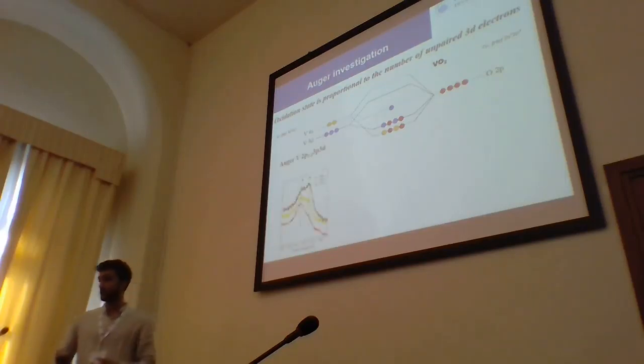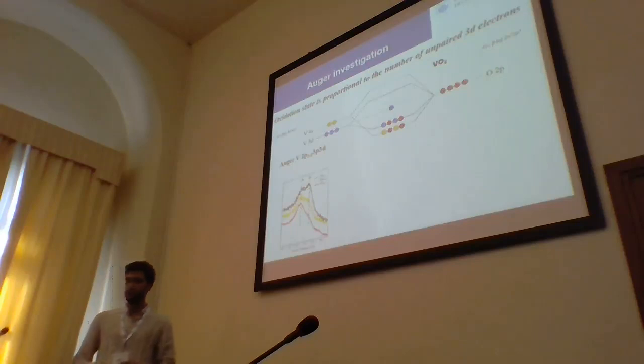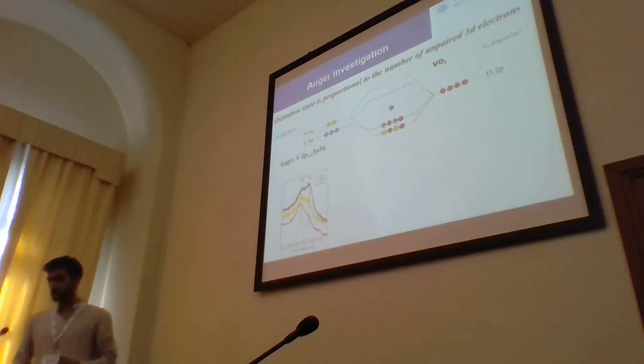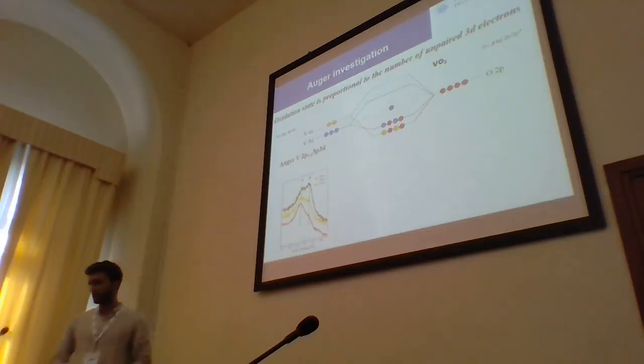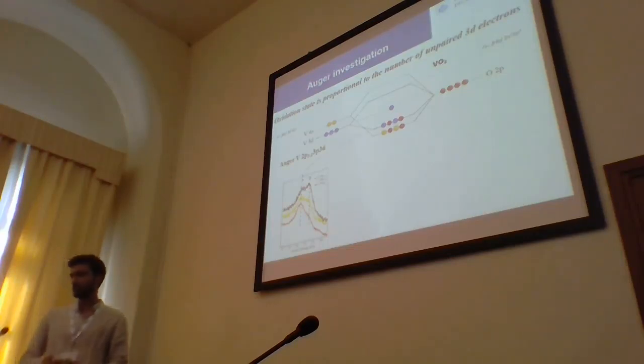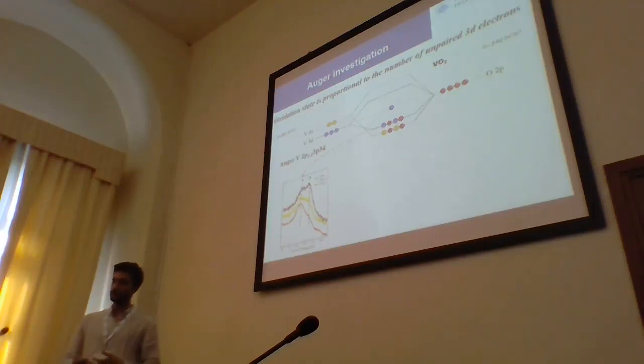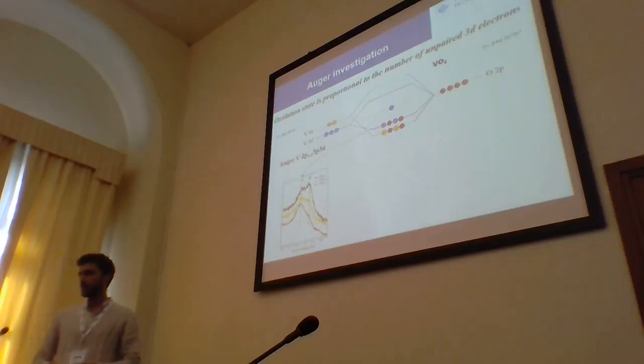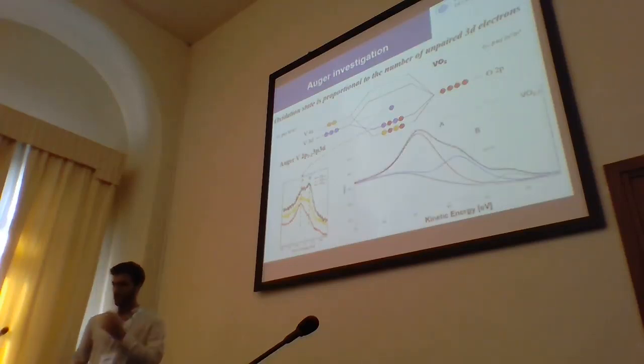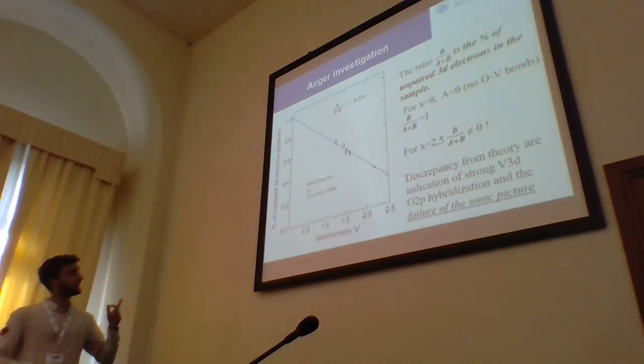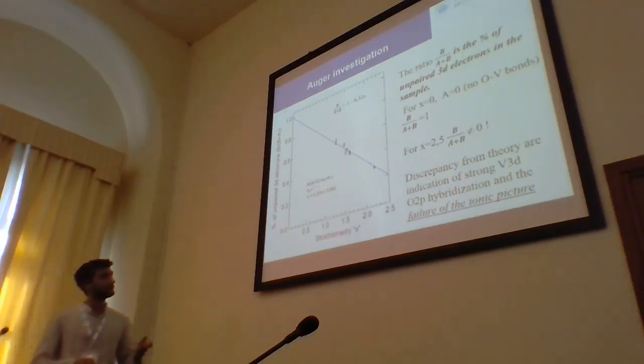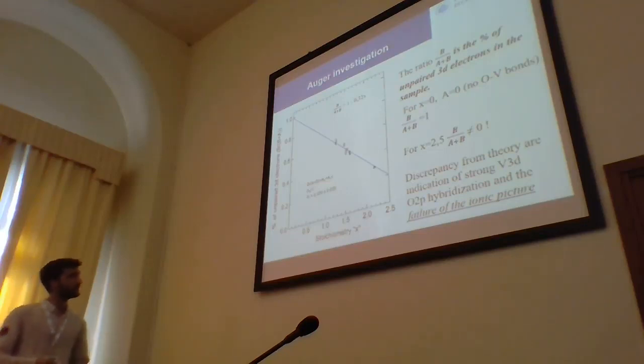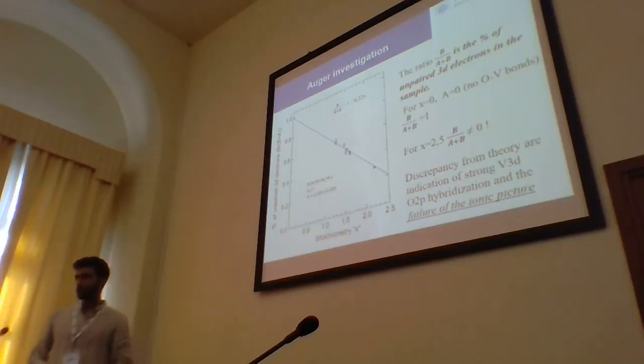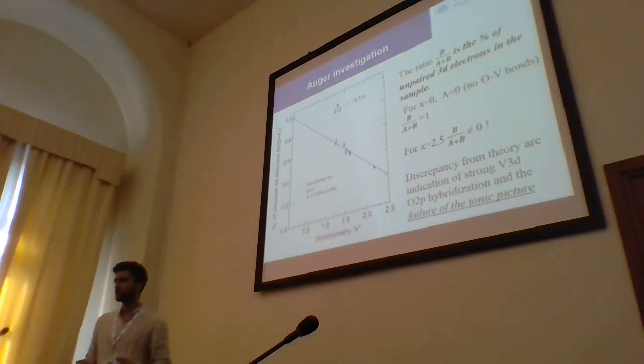So looking at the Auger 2p 3/2, 3p, 3d, we see that as a function of the oxidation state, there are two features that, using all my imagination, I called A and B, which evolve with the oxidation state. I was able to link the A feature to the 3d electrons of vanadium which are bound to oxygen, and the B feature to the unpaired 3d electrons. Again, fitting these two features, I was able to extract quantitative information, and in particular the ratio of the area of the B feature with respect to the sum of the A plus B features is the percentage of unpaired 3d electrons in the sample. As you can see, this quantity as a function of stoichiometry can be fit by a linear relation.